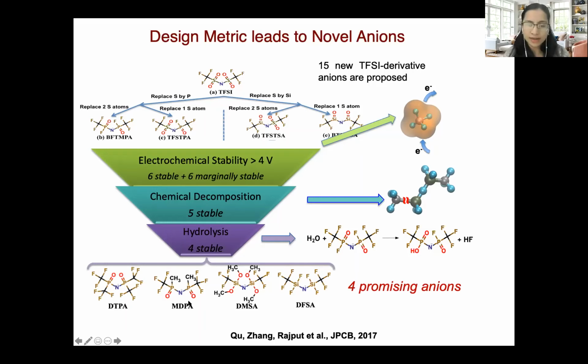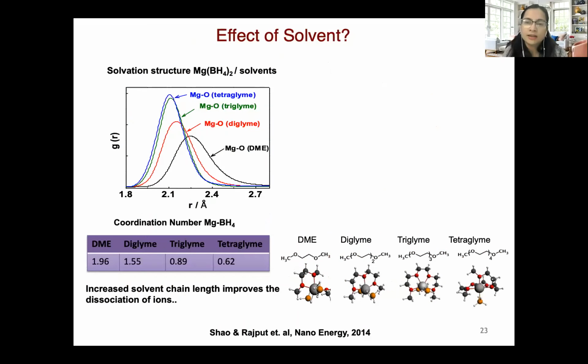However, we understand that computationally derived new molecules are not always the best molecules for synthesis, and it's not always possible to synthesize these completely new molecules. So we also tried to enhance the performance of existing magnesium electrolytes, and we studied the effect of ligand in magnesium borohydride salts. And here we considered a magnesium borohydride salt with Glyme solvents, and we increased the chain length of Glymes from DME, which has 2 oxygen atoms, all the way to tetraglyme, which has 5 oxygen atoms.